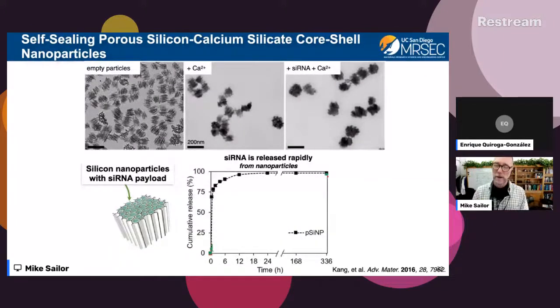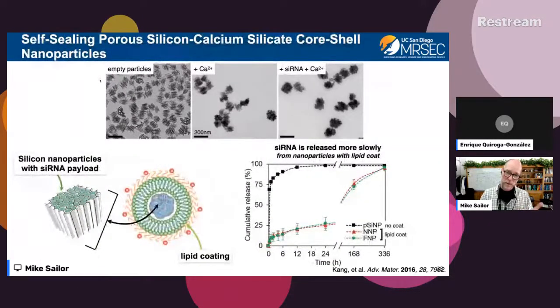We got a lot of RNA in there, but the challenge was it dissolved out too quickly. You can see this in the bottom trace here, the particles gave up the nucleic acid within just an hour or two, almost all of the nucleic acid had come out. And by 18 hours, basically our particles had completely dissolved. And so that dissolution rate was just way too fast for us, and it was not going to be effective. And so that's where we borrowed this trick from the lipid nanoparticle community.